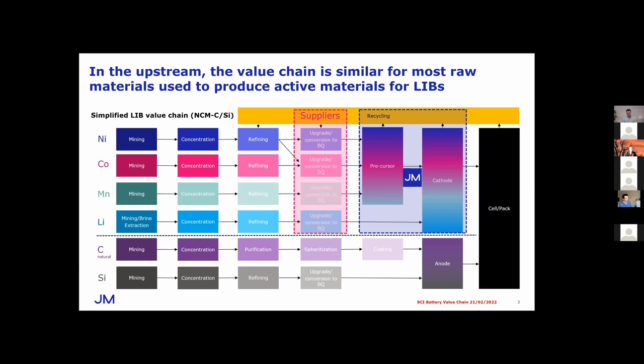For the anode side at the bottom there, it's similar, except there isn't so much of a precursor step where you would blend materials together. Conventionally, you would take your carbon in graphite form, synthetic or natural, as shown here, and take it all the way through to an anode. However, with the advent of silicon-doped graphite anodes, we are seeing silicon material enter there, and potentially, of course, maybe a complete silicon anode in future, should the technology mature enough to stabilize that material for long cycle life.